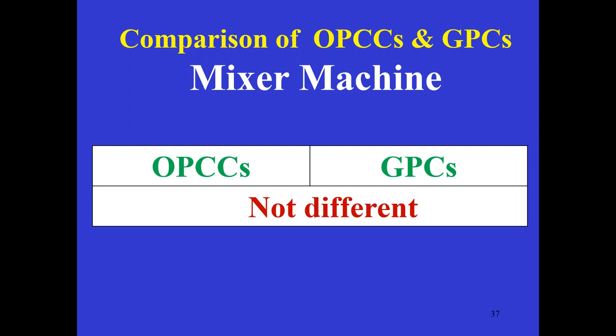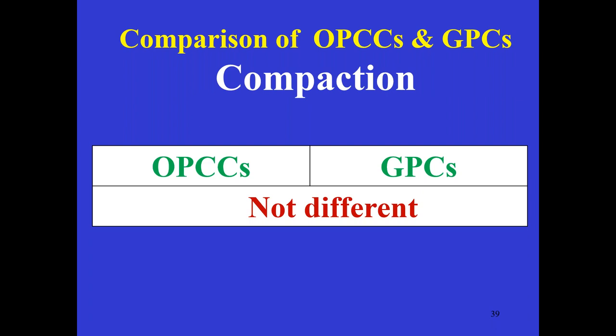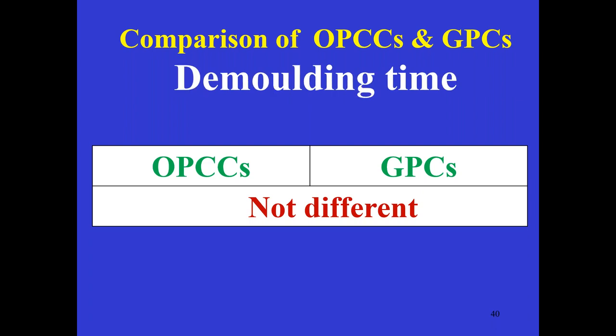And in the laboratory also, usually we should use only a pan mixer or a screw type, not the drum type. Drum types are really not good for the development of the mixes, any OPC mix also. So especially smaller drum types are very bad. So we must buy always a pan mixer or a screw type mixer and start working on the materials. And they are not very costly, it is available. Molds, there is no difference. Compaction, there is no difference.